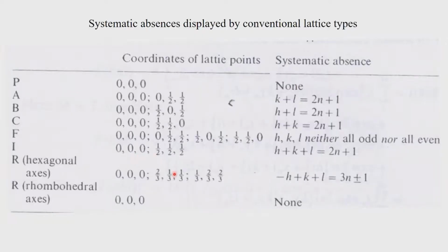If we have a rhombohedral cell and fix it in a hexagonal lattice, then we have this problem, and this problem is because the rhombohedral axis now will show coordinates of these 3 positions, and that is the property of the rhombohedral cell. It is a special case of the hexagonal lattice. All hexagonal lattices will not show. So, in principle if we have a hexagonal system which is indexed as a hexagonal system, you have A equals B not equal to C, alpha beta 90 degrees, gamma 120, and then it shows rhombohedral symmetry, then you will have these systematic absences. So, this is very interesting.